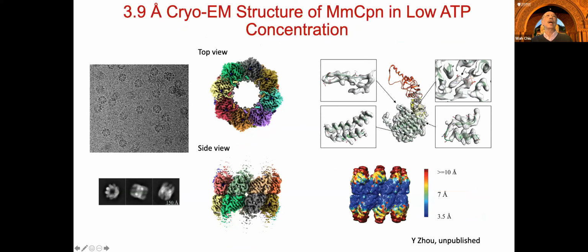Instead of seeing this, all the polypeptide chains closed up together, we see these are open conformations. And in fact, the resolution on average is around 4 angstrom rather than 2.3 angstrom resolution. And if you measure the resolution distribution, each of these protein subunits varies, with very high resolution close to the equatorial domain and low resolution going to the apical regions. So that triggered in our mind that perhaps each of these particles that we see, on average, we can derive an average structure, but in reality, each of these subunits may be different in each of the particles. So we then undertook another data processing step to classify the protein subunits in each of these particles.